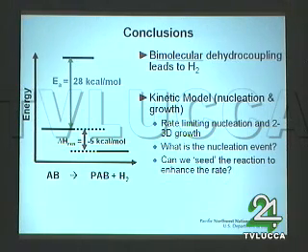And so that's going to make it a lot harder to just pressurize to put the hydrogen back on. But some of the stuff we've done with the scaffold material that we've published, and it was on the poster, the enthalpy actually changed to almost thermal neutral. And so we're pretty excited to demonstrate for the first time that you could just pressurize this and see hydrogen go back on here. And we have a Sieverts apparatus coming from Carl next month, and we want to do the measurement at high enough pressure so we can demonstrate this reversibility. It'll give us some more information about the enthalpy.